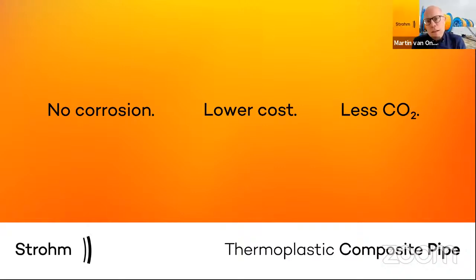That's a very good question, Mario. I would not have expected anything less from Mario, of course. And in fact, in some cases, the tensioner loading, so the installation case, can be quite important. Can be a very important load case. In our case, fortunately, it is not driven by tensioner, and the wall thickness is mostly driven by internal pressure, sometimes by external pressure. So, for instance, when we have 6-inch ID, I have it here.